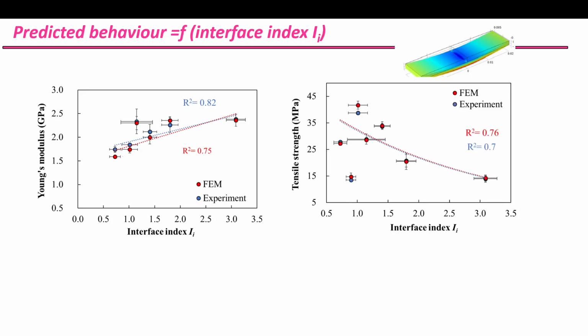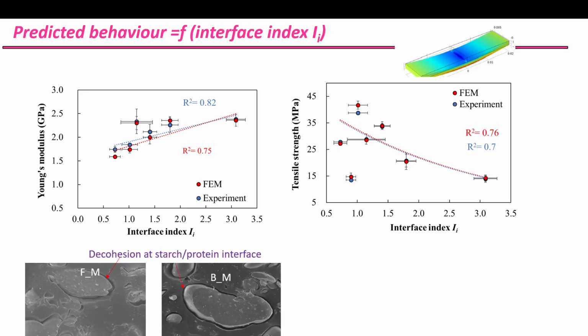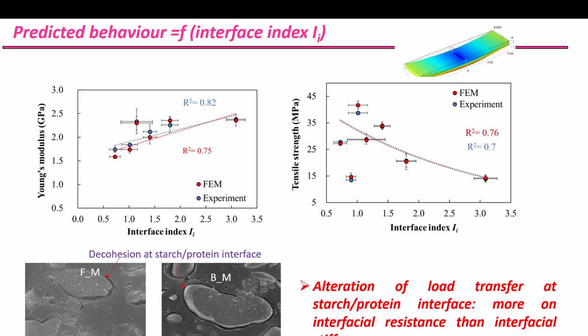If you look at the tensile strength as a function of the interface index, we see more negative correlations, which could also be explained by the fact that you have a weak link between the two phases. The examination of the SEM fractography shows clearly the decohesion between the starch and the protein, and the explanations of the two curves can be sketched as follows. The alteration of the load transfer at the starch-protein interface could be more related to the interfacial resistance than to the interfacial stiffness.